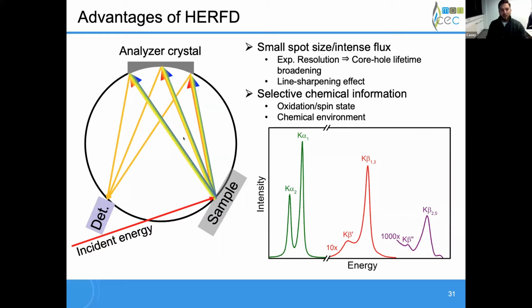And out of this, we get a line sharpening effect, which is really advantageous and why it's actually called HERFD at the end. With HERFD, we could also choose other lines, for example, in the K beta 1,3 or K beta prime, or even in the valence core region, to get other selective chemical information and look at the absorption spectrum as a function of more specific processes. So it's really overall a very powerful technique in XAS.